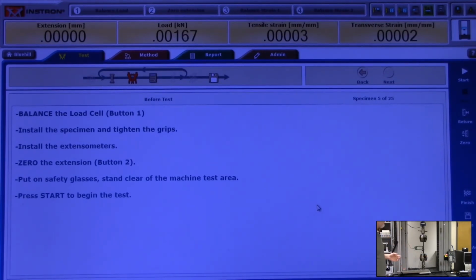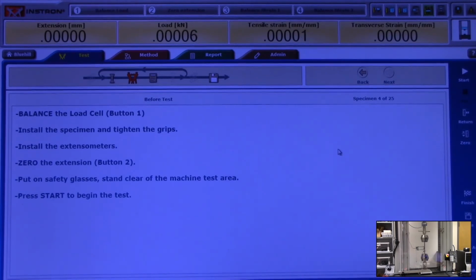This one is a lot more robust and designed to withstand the abuse it's going to take when the specimen fails. It's a little bit larger. It's got a 50 millimeter gauge length rather than the 25.4 millimeter. And that's better suited for composites, which typically tend to be longer. So we have a longer gauge length. Okay, I've got the transverse installed as well, but I'm going to remove the transverse extensometer about halfway through the test so it doesn't get subjected to the abuse when the specimen fails. All right, I've got everything loaded, zeroed, balanced, etc. And we are now ready to test.